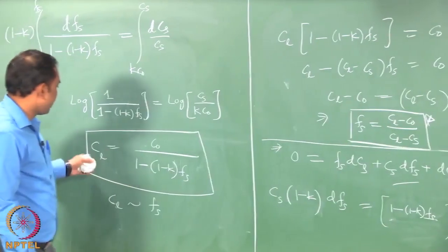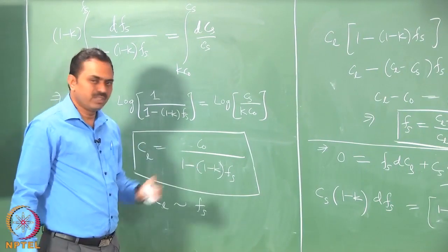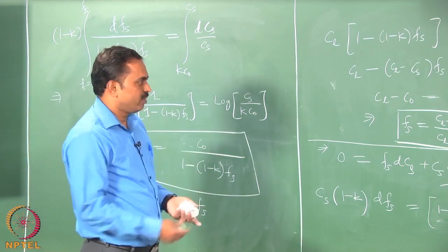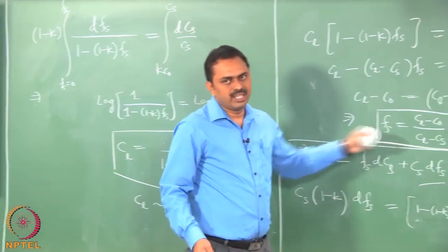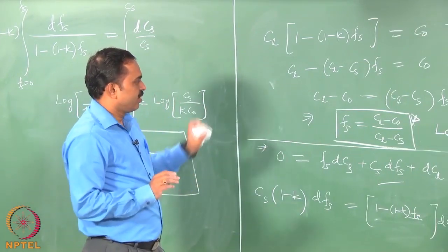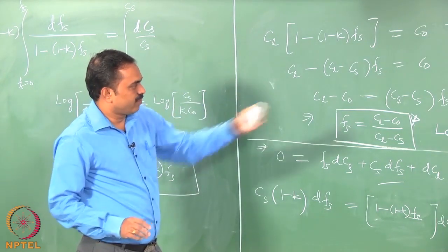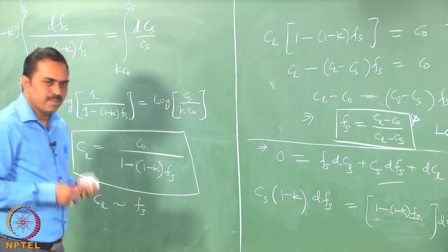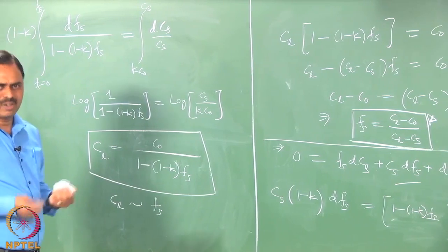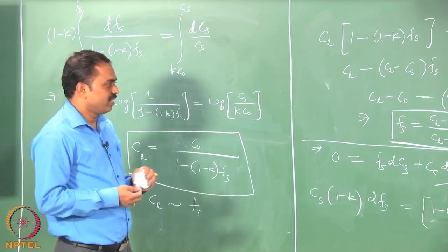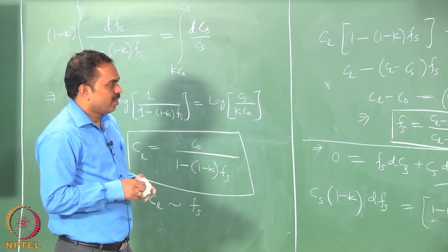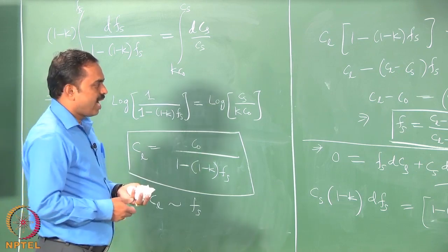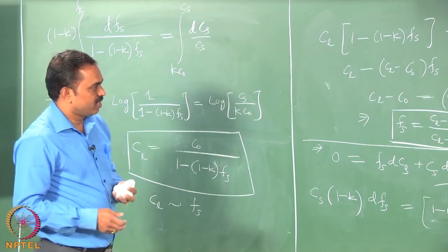It is actually giving you the liquid composition as a function of the solid fraction or liquid fraction, and under the situation that it is fully mixed in both solid and liquid, you retrieve the Lever rule. Okay. So, this is one thing that we can bring from the relationships that we have drawn. Okay. And when is it applicable? Whenever the complete miscibility is there in the liquid, which is generally not possible in a fast process such as welding. That's the reason why Lever rule is not applicable most of the time to understand what would be the composition variations that are happening at micro scale. And we now see that it is originated because of the assumptions that we started off.